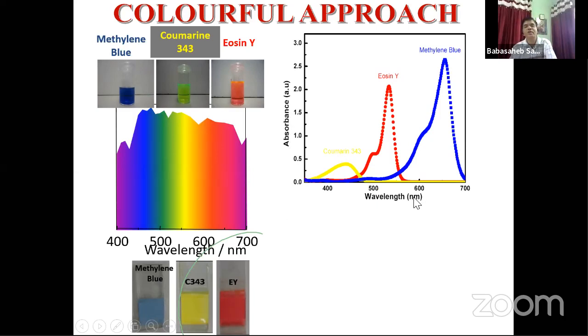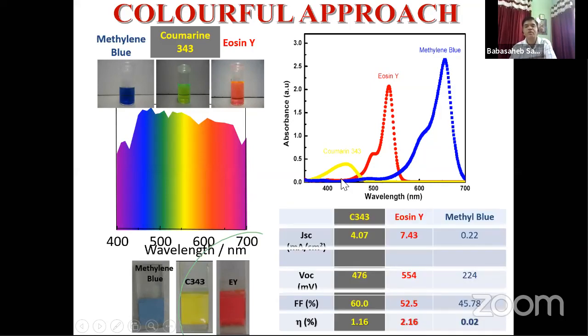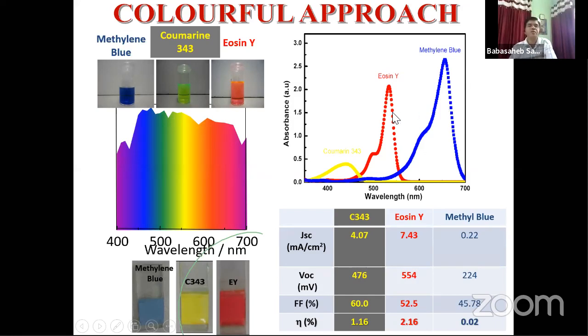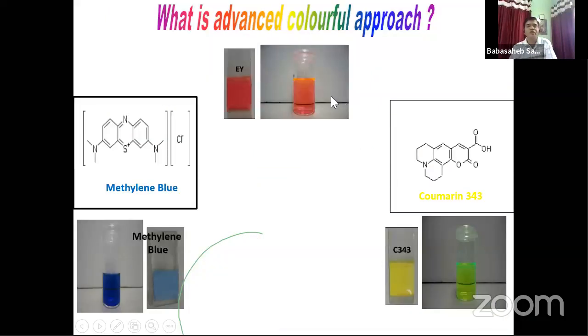This is the absorption against the wavelength spectra. This is for coumarin, this is for eosin Y, and this is for methylene blue. Each dye has its own absorption region in the visible part of the solar spectrum, and depending upon its absorption, it can show different efficiency. The coumarin dye gives an efficiency of about 1.16%. Eosin Y, as we just saw, is about 2%, and methylene blue is 0.02%, because it does not have a carboxylic group, it has just a chromophore group. Although it has very high absorption in the solar spectrum, it shows very low efficiency because of the non-availability of the carboxylic group, which can attach very well with the zinc oxide.